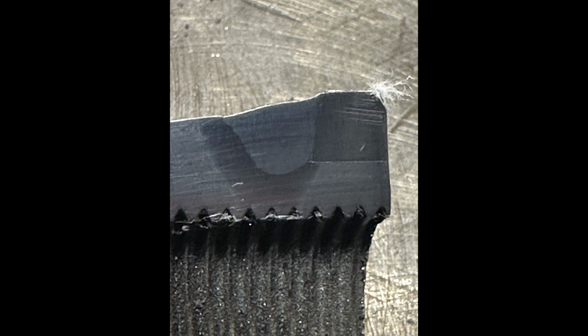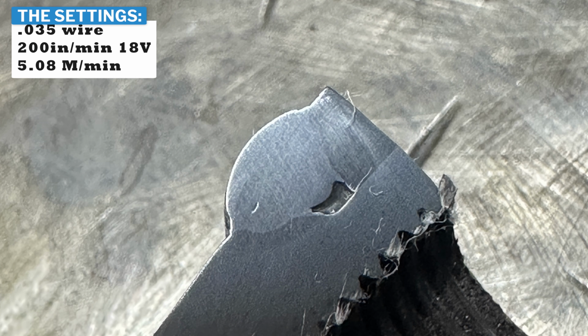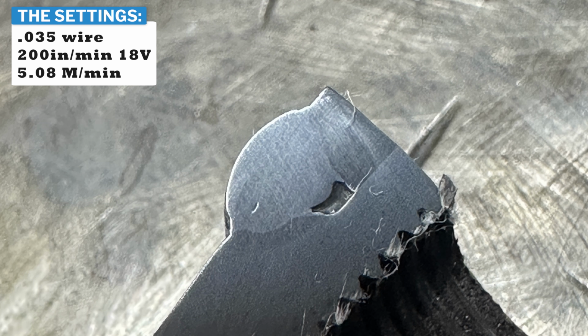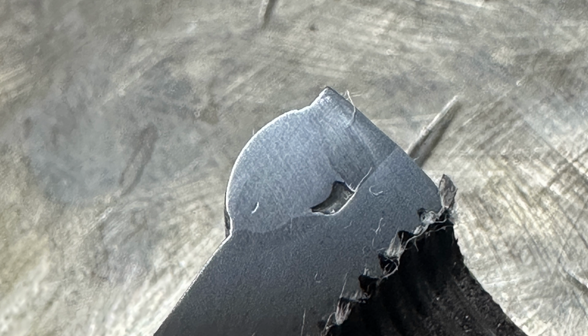Speaking of not knowing what's inside, let's look at the cold stack of dimes. So here we go. The proof is in the pudding. These cold settings, which is what is commonly used to do that stack of dimes look, granted I didn't do the best job on it in this video, but those are the settings. This is the end result. Now you can tell the same amount of weld material was put down as the other welds, okay? It's just that this did not fuse in, and most of the weld is actually above the plates, not really doing much to help you.